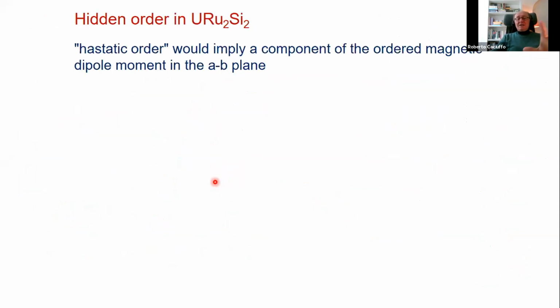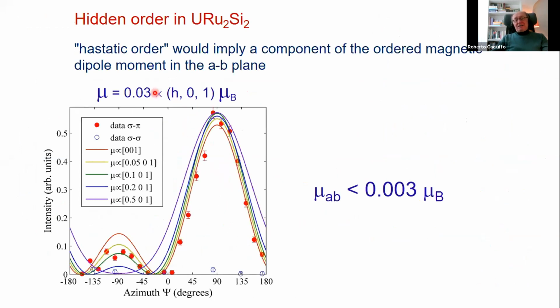Moreover, hastatic order model would imply the appearance of a component of the ordered moment also in the ab plane. This can be checked, and you see that adding such a model component in the plane is increasing the width of the main peak in the azimuthal dependence, and is changing the intensity of the smaller peak. So an analysis of the data showed that if such a moment component is present, it will be smaller than 3 millibohr magneton, whereas the theory predicts a moment as large as at least 0.1 Bohr magneton.